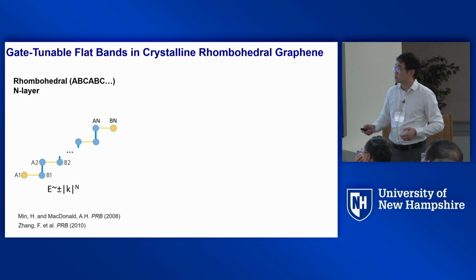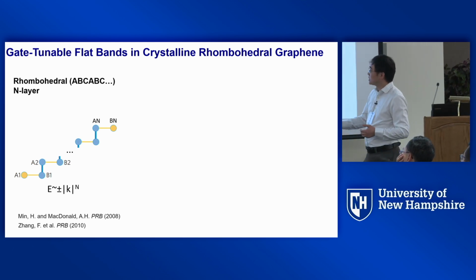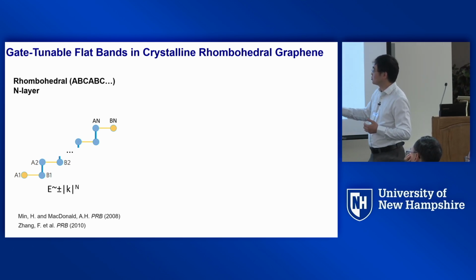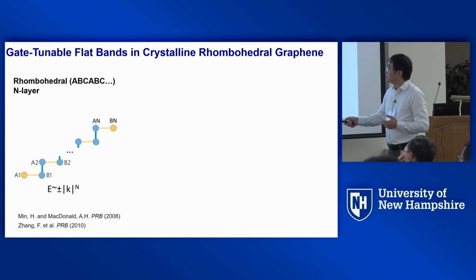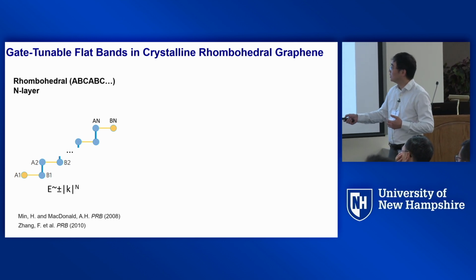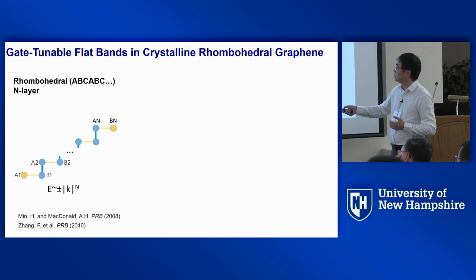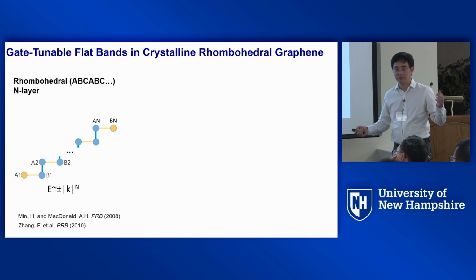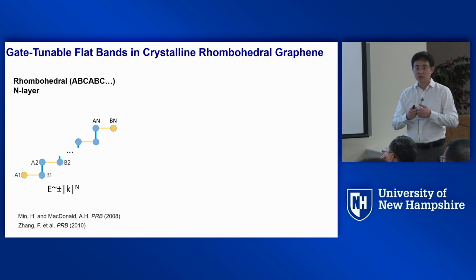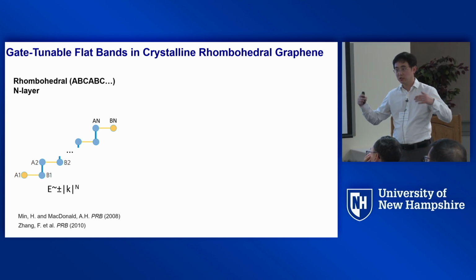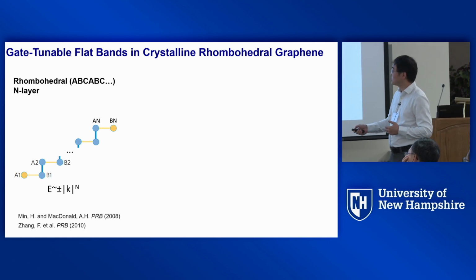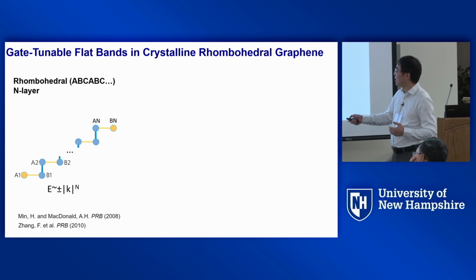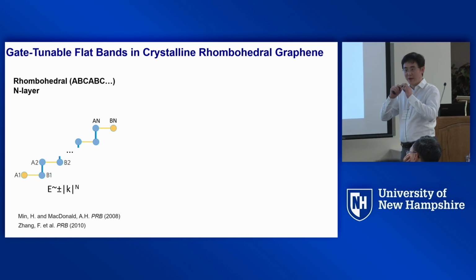Why is rhombohedral interesting? Rhombohedral, if you look from the side, has this kind of staircase structure. You can think of this as a big molecule, and all the orbitals in the middle hybridize, forming bonding and anti-bonding states. So they are not relevant for the lowest energy band structure. What's really relevant are these two dangling bonds. They are degenerate, and that gives you zero band gap.